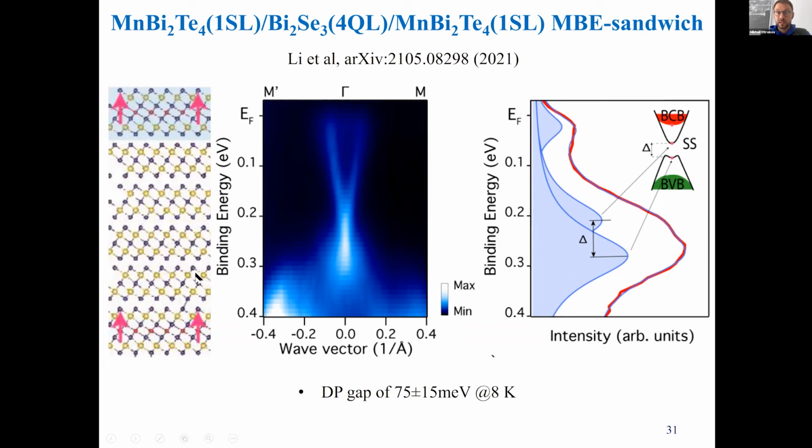Formally, this system is a quantum anomalous Hall insulator, but in practice, the Fermi level appears to be in the conduction band, so we have to lower it down, either by adding antimony or improving the growth technology to avoid defects, because obviously if the Fermi level is so high, there are defects.